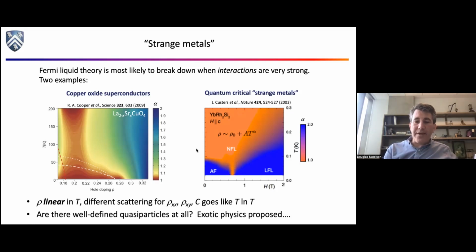But the thing that's weird about them at first glance is that the power law is wrong. Remember, I told you the power law goes like some residual resistivity due to dirt in your sample plus temperature to some power. And for a Fermi liquid, that power should be 2. But what you can see here in one of the copper oxides and here in this material we're going to talk about later, ytterbium rhodium 2 silicon 2, is there's a big region where instead of that power law being 2, the power law is 1, right? The resistivity is linear in temperature. It turns out also the heat capacity does odd things too. But this may seem like not a big deal. I mean, okay, so the power law is 1 instead of 2.